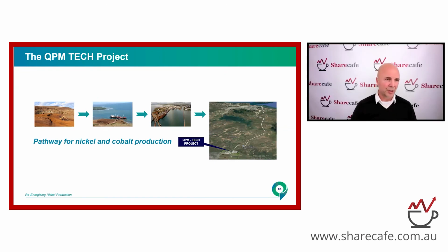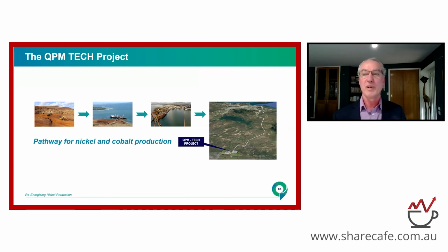And then there's kind of a technical question here. I know we've got a couple of analysts online. The DNi process that you're using has a low carbon footprint, it's quick, less wasteful, no tailing dam is required. Now, with regards to battery performance, how does your class 1 nickel product compare, and where does it sit on the cost curve? So it's a class 1 nickel product. It's just high purity nickel and cobalt sulfate, the same as anyone else produces, however they're producing it. So it's the 3 ppm of iron, and the 2 ppm of this, and the 20 ppm of cobalt in the nickel, and so forth. So it's just the high purity feedstock. So it's exactly the same as nickel and cobalt sulfate produced by BHP in WA or Terrafame in Finland.